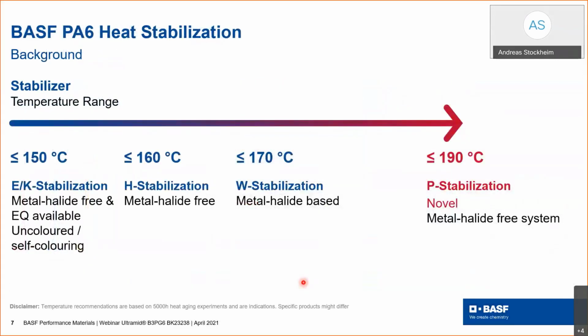In addition to this new heat stabilization, we achieved a much higher heat stabilization of our PA6, as you can see here, and I think some of these stabilization systems are already known to our customers. You see the E and K stabilization system, the H stabilization system, and normally within ICE and powertrains W stabilization is used, and with our P stabilization, which is metal halide free, we achieved temperatures up to 190 degrees C.